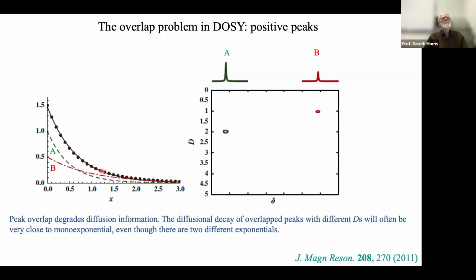Let's suppose that we've got two compounds. One of them's got a diffusion coefficient of 1 times 10 to the minus 10 meters squared per second, biggish molecule, kilodalton or so. Other one's a bit smaller, diffusion coefficient of 2. Here are our diffusional decays. Faster decay for the smaller molecule, A. Slower decay for the larger molecule, B. But, you know, if I were in the teaching laboratory and an undergraduate student showed me these data, I would say, yeah, that looks a pretty good exponential.